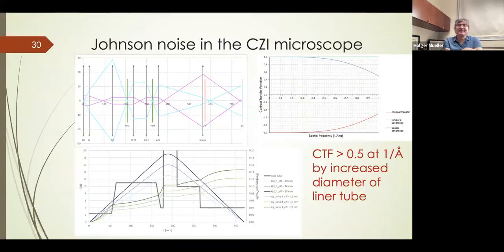Will Johnson noise hurt this? And it turns out by increasing the diameter of the beam liner tube, the CZI microscope can still reach a contrast transfer function that is larger than 0.5 at 1/Å spatial frequency. Despite the Johnson noise issue. We're extremely grateful for Thermo Fisher to be so collaborative and consider these modifications.